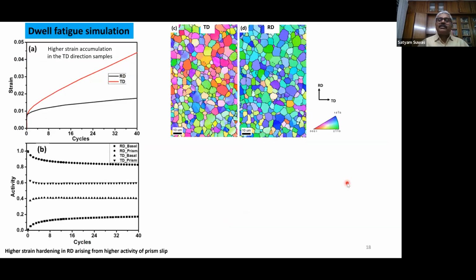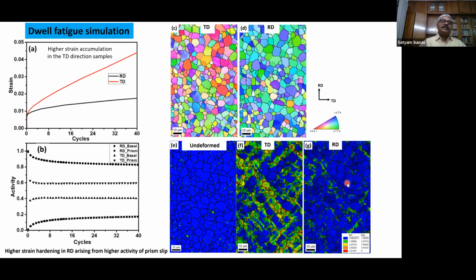Then what about fatigue simulation? So these are under tension tests. In fatigue tests, what we have seen here is that the predictions said the RD samples have lesser strain accumulation, as we could see, and the TD samples have higher strain accumulation. And this correlates with the basal slip and prism slip activities here.